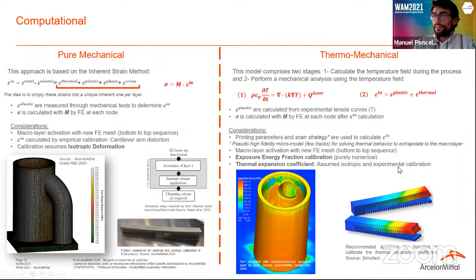And then, even though this model does not need calibrations, SimuFact recommends two types of calibration. One is experimental calibration, with a similar cantilever geometry, which is used to calibrate the thermal expansion coefficient and then calculate the stresses due to the thermal stresses. And another is a pure numerical calibration, where we divide the laser energy input from the machine into the fraction of the laser that is used for melting and bonding the powder with the part, and then the fraction of the laser energy that is dissipated by the surroundings and the previous layers.